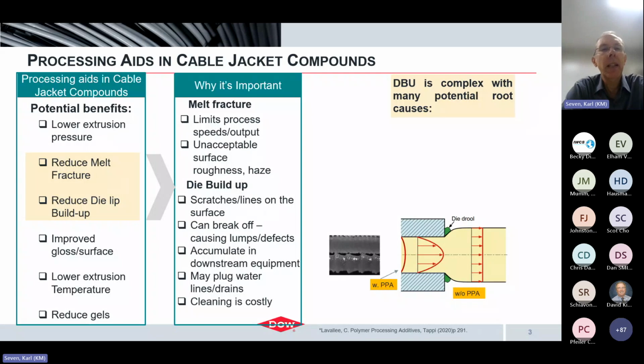Die lip buildup is another frequent issue that occurs. Die lip buildup is that unwanted accumulation or residue that shows up on the surface of the die, like I show here in this picture. Over time, throughout the extrusion process, this buildup gets more severe, and it's possible that the line may need to be shut down in order to clean this residue off. If this residue becomes very severe, it can, of course, break off. It can plug up extrusion cooling lines and so forth. It can also have an impact on the surface quality of the extruded product. And so, obviously, it's a problem that needs to be addressed. And this can be